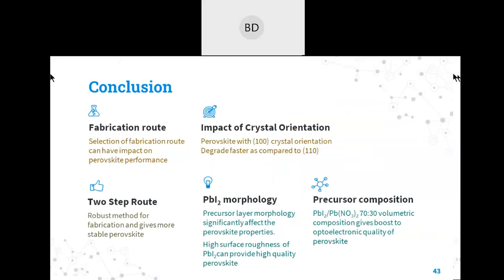So reviewing some conclusion points, we understood that the perovskite film properties are fabrication route dependent. If you use a different kind of perovskite, there will be differences in the properties, and there will be differences in the degradation routes as well. We understood that the crystal orientation of the perovskite has a very important role in governing the degradation mechanism. If you use the 100 kind of crystal orientation, then methylammonium is on the top, and it will degrade faster. We understood that the two-step route has little robustness toward moisture ingress and provides a comparatively stable perovskite. We understood that the PbI2 morphology has a significant role in governing the perovskite structure.